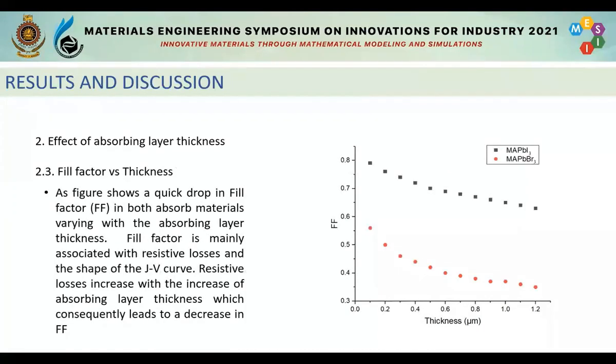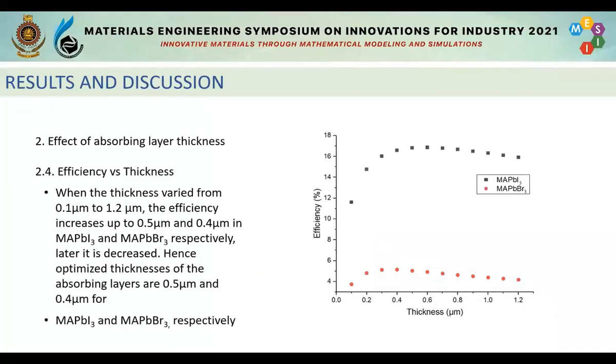The fill factor versus thickness graph shows a quick drop in fill factor in both absorber materials with varying absorbing layer thickness. Fill factor is mainly associated with resistive losses and the shape of the IV curve. Resistive losses increase with the increase of absorbing layer thickness, which consequently leads to a decrease in fill factor.